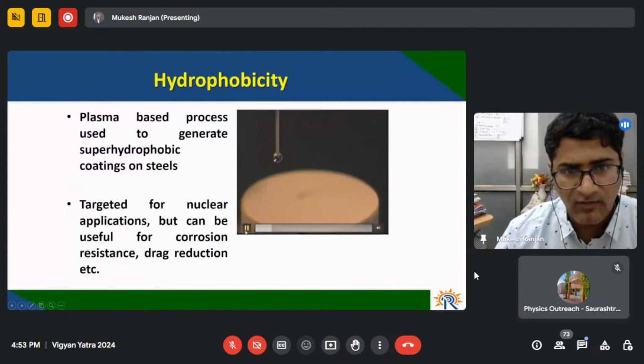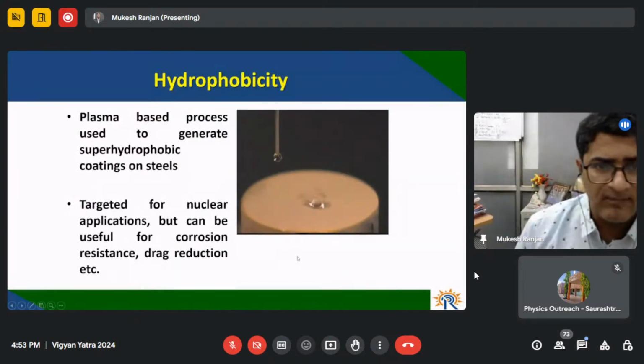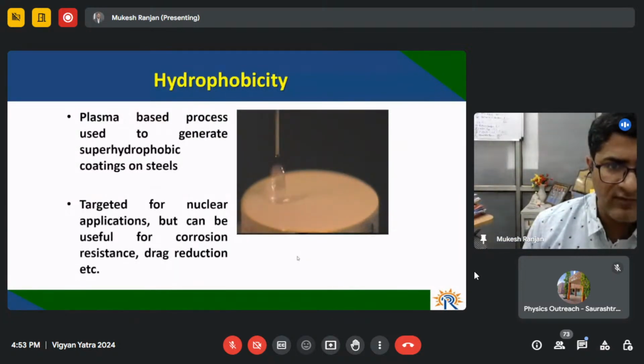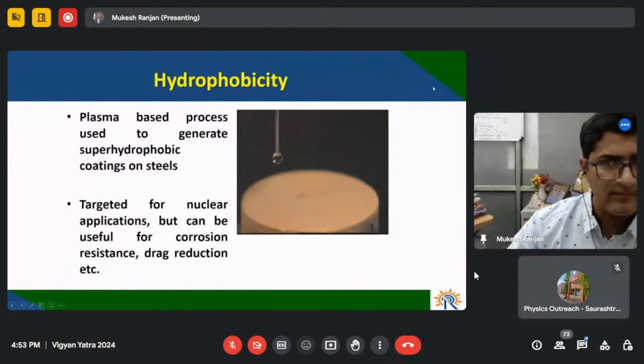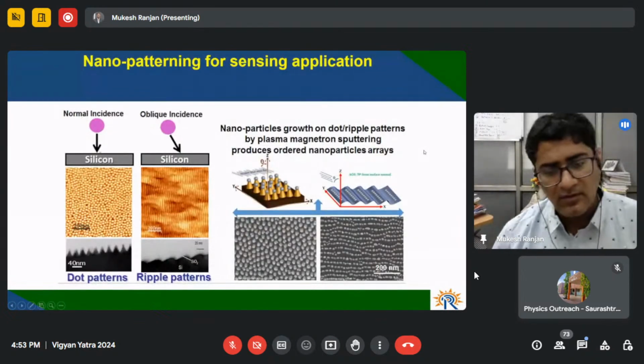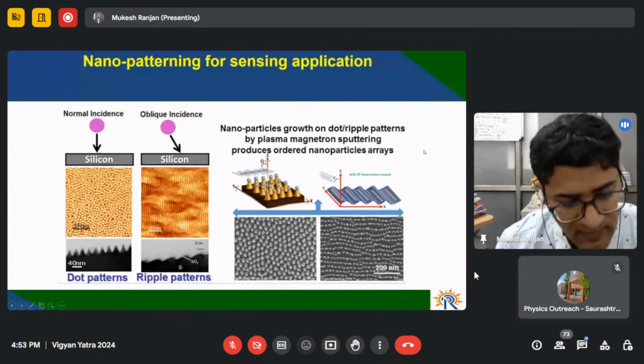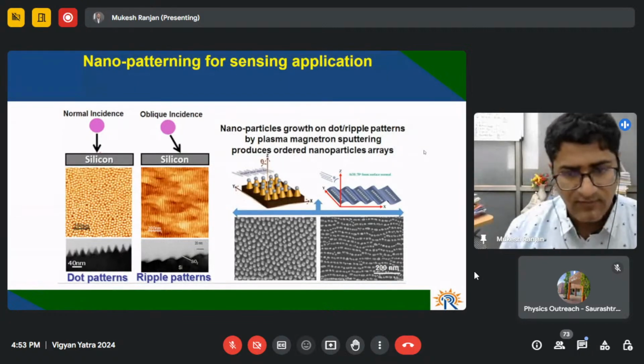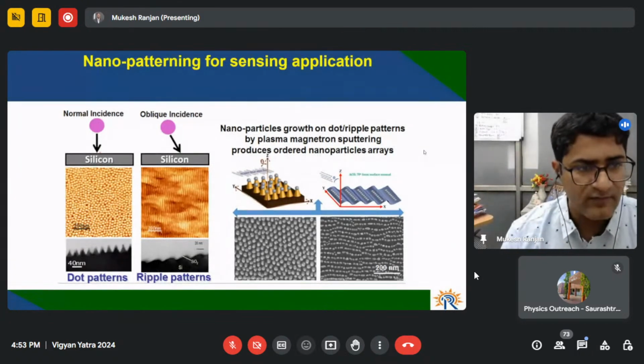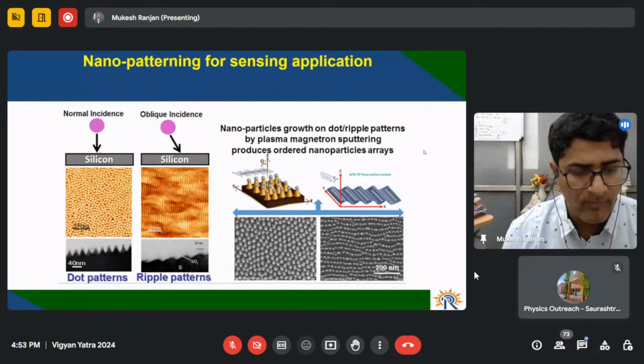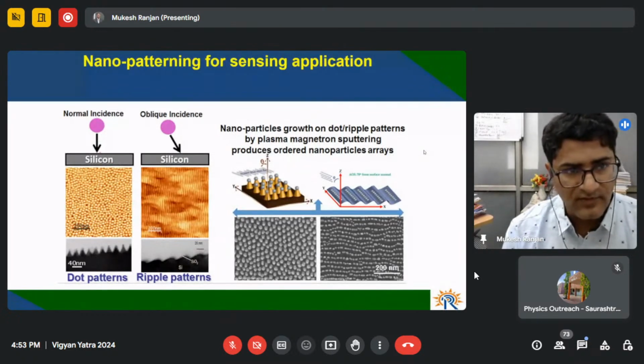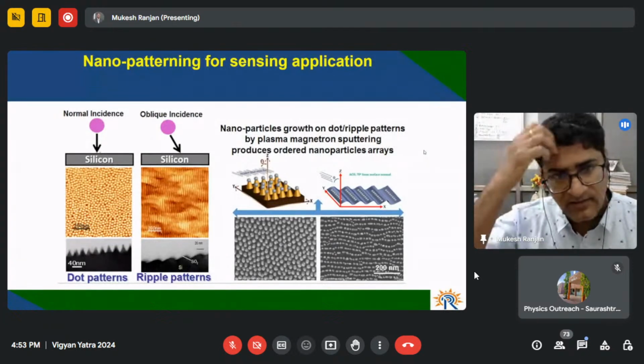So this is an example where we can make Teflon using the plasma process. We can make a Teflon-like coating on the surface, which is super hydrophobic in nature. So I told you that plasma makes a nanostructure on the surface, and that can change the wettability of the surface. So it can make it super hydrophobic, it can make it super hydrophilic. So this is one example application of the nanopatterns, but it has many other applications.